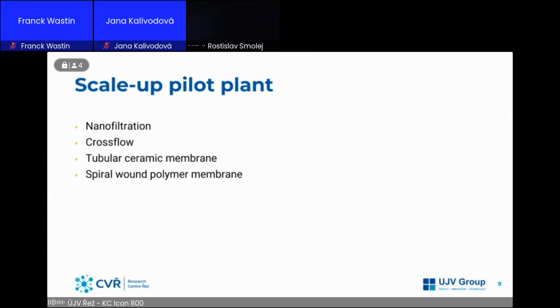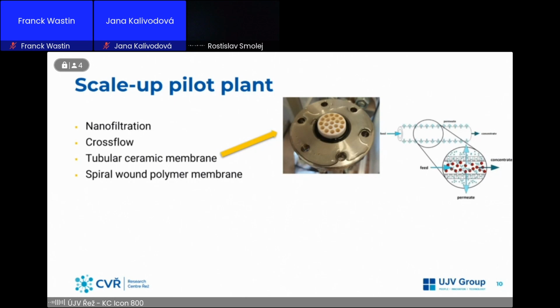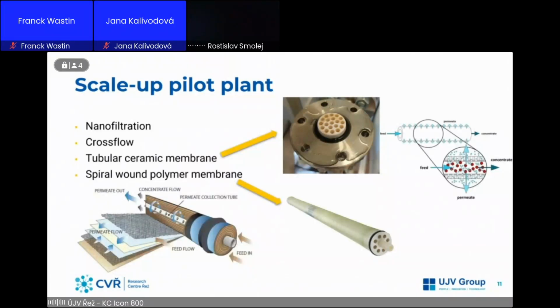After the tests in the laboratory, we then moved to our scale-up pilot plant. We've chosen nanofiltration because we decided to prioritize the higher rejection rates, even though it meant that we will need a bit higher pressure to apply, which would lead to higher energy costs. Then the cross-flow setting, because the cross-flow setting lowers the probability of the membrane fouling. And then we tested two types of membranes, the tubular ceramic one, as you can see on the slide, and the spiral wound polymer membrane.